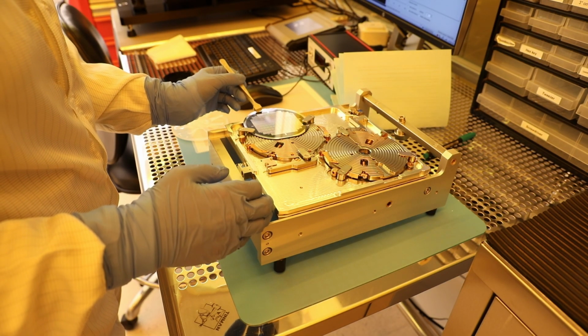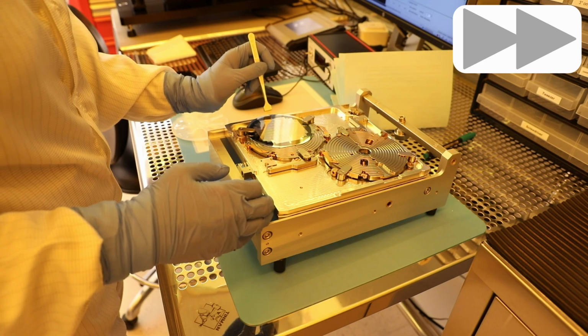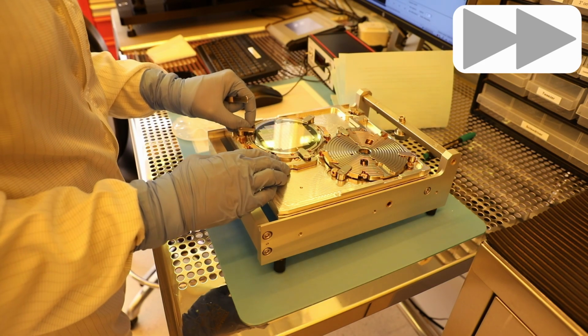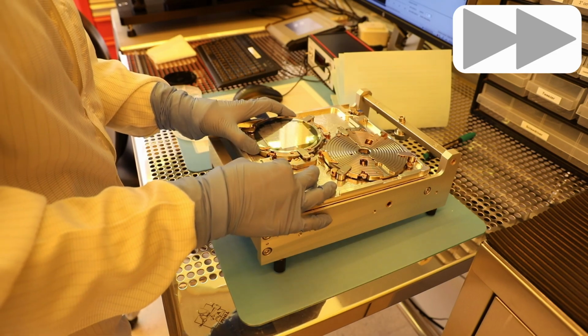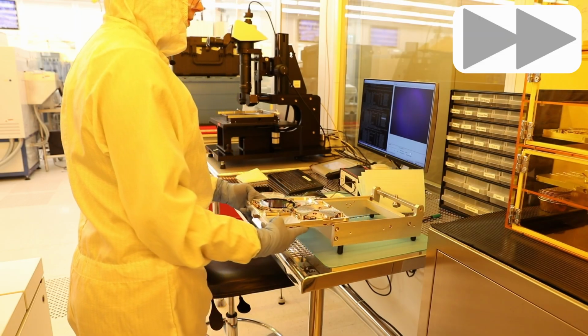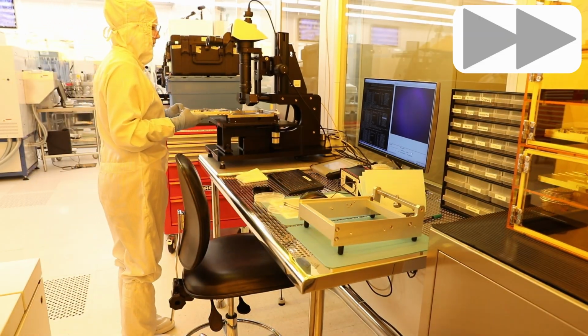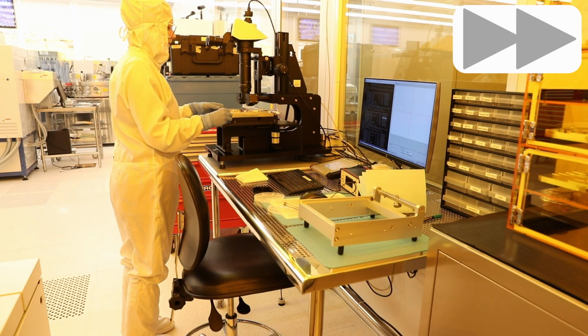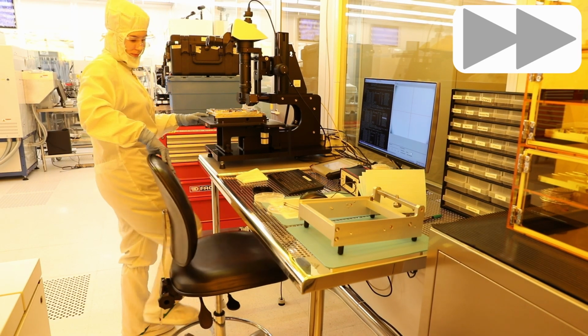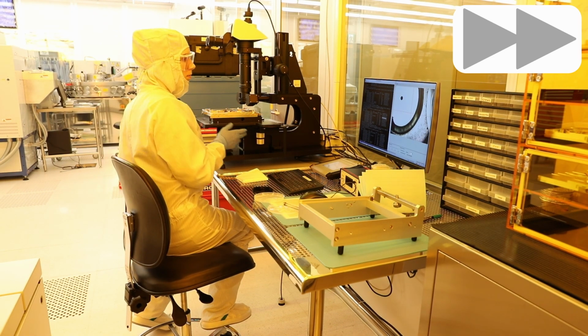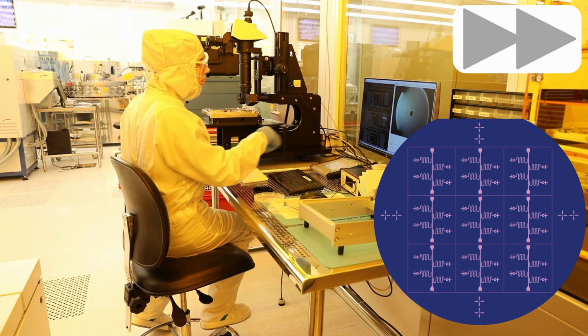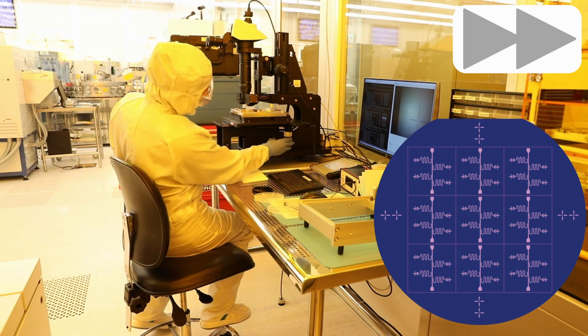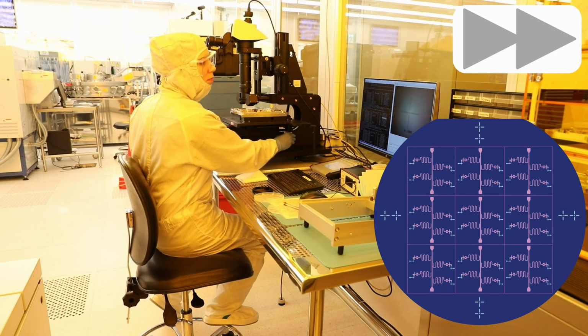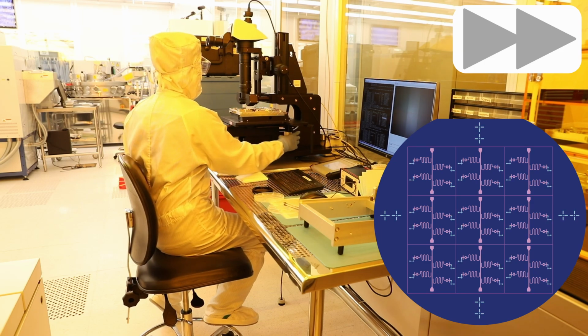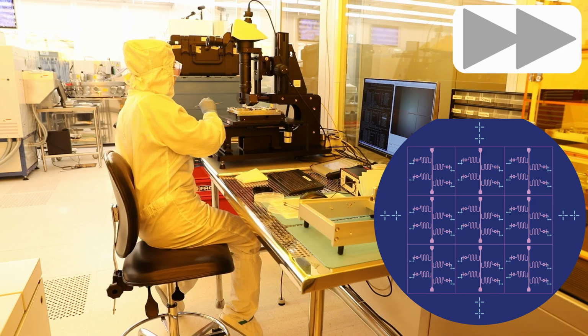First, I'm going to mount the wafer on one of these specialized loading cassettes. They are a delicate piece of engineering, very fragile, very expensive, because they are machined with extreme precision to enable me to finely adjust the rotation and tilt of the wafer. They also act as a very stable point of reference to the exact position of the wafer in the system, and also to the position of the alignment marks I made on the wafer in the previous patterning step, so that both patterns made in these two separate lithography processes can overlap and match as they should.